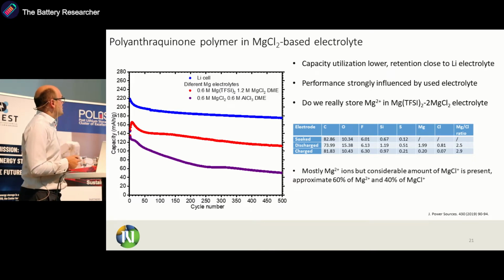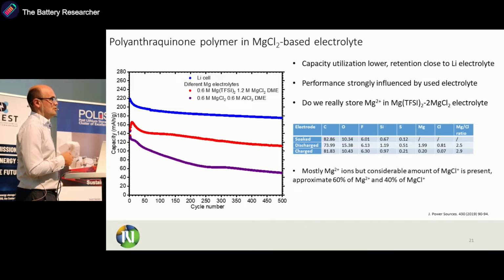And we can see that there is quite significant difference. The theoretical capacity should be somewhere here, but already in lithium we don't reach it. We are reaching only 220 milliamp-hours per gram, and then, although this is a polymer, there is a fade of capacity. And then in magnesium, there is a big difference between magnesium TFSI and aluminum chloride-based electrolyte. We can see that this one has much higher maximum capacity and also better capacity retention.